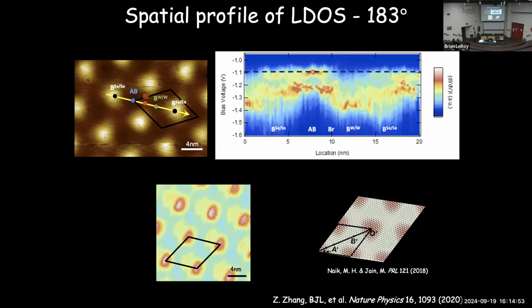And the difference between these two is all coming from the fact that you have this 3-atom structure in the tungsten selenide, and there's a difference between the stacking of 0 degrees and 180 degrees. And so that's leading to different confinement of the electrons and different wave functions in the material.